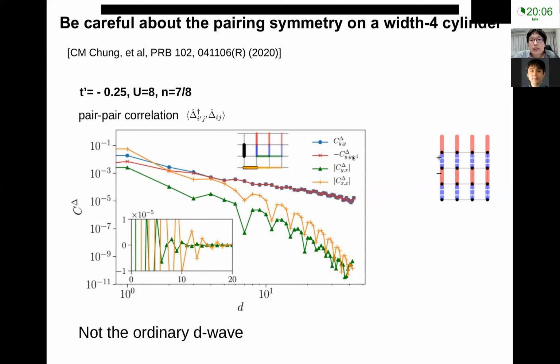We found that the pair-pair correlation shows that the pairing symmetry in this system is actually not the ordinary D-wave that we expected. You remember the ordinary D-wave has opposite sign for all the vertical correlation and the horizontal correlation. But here instead, we found this kind of pairing symmetry.